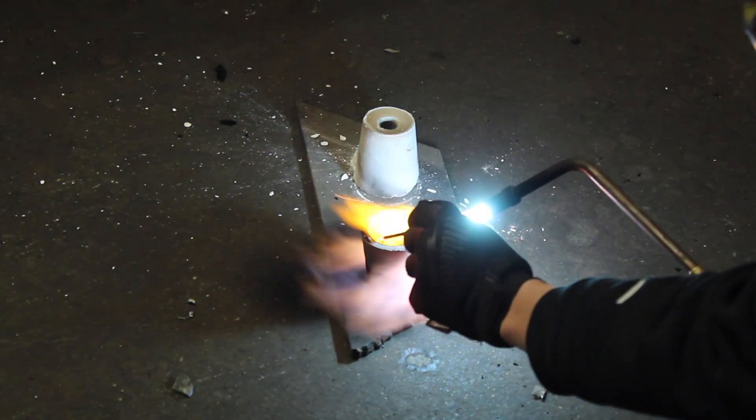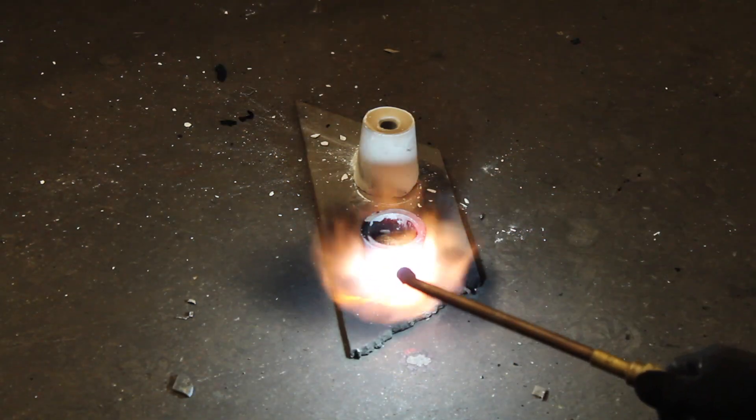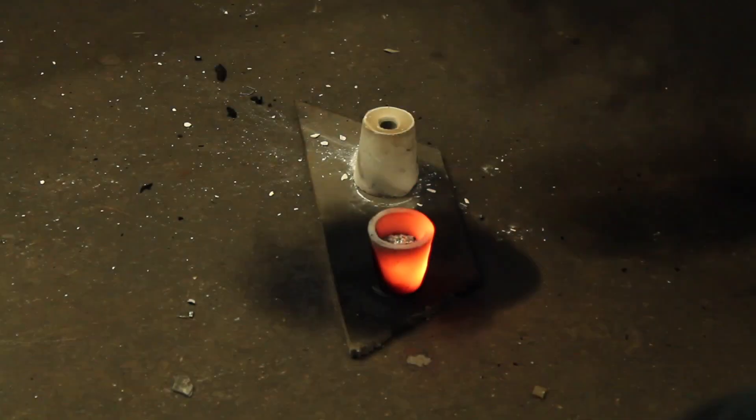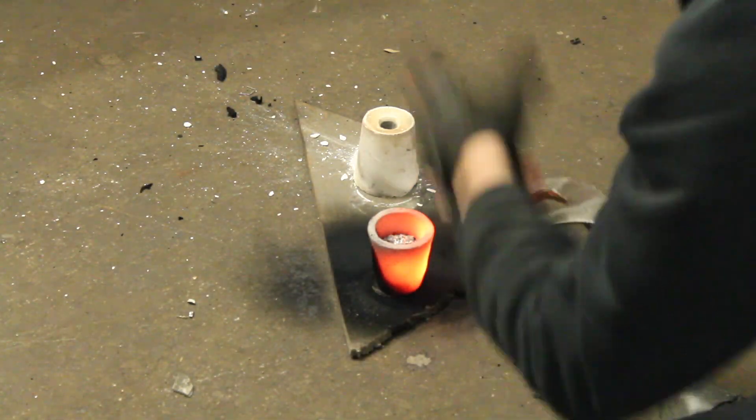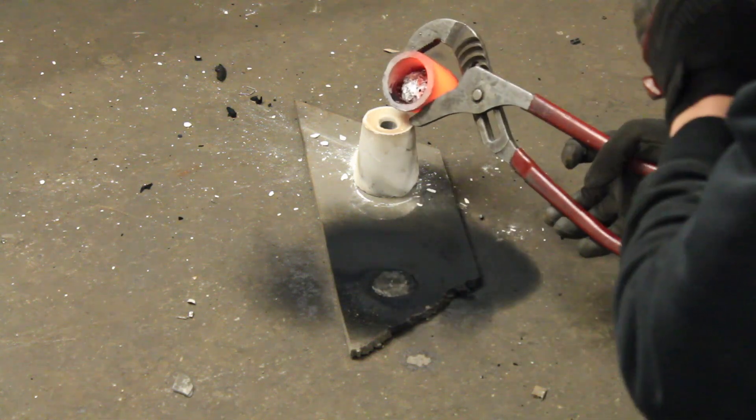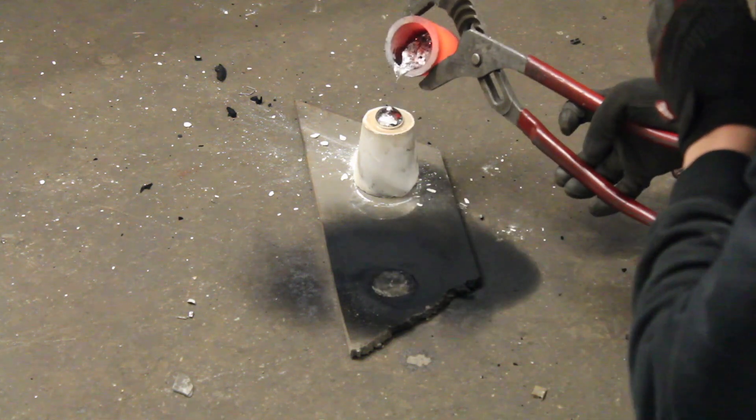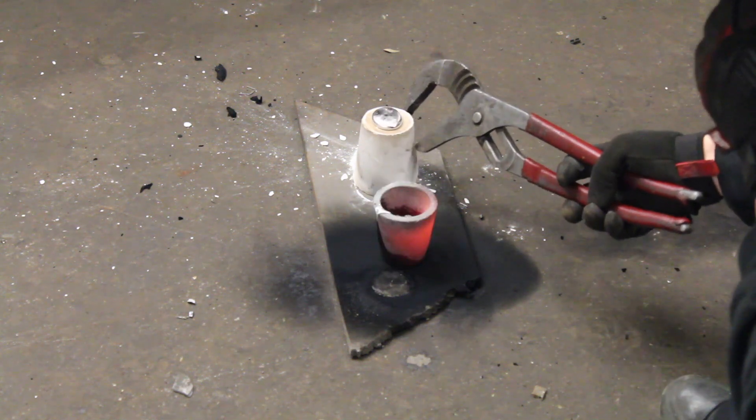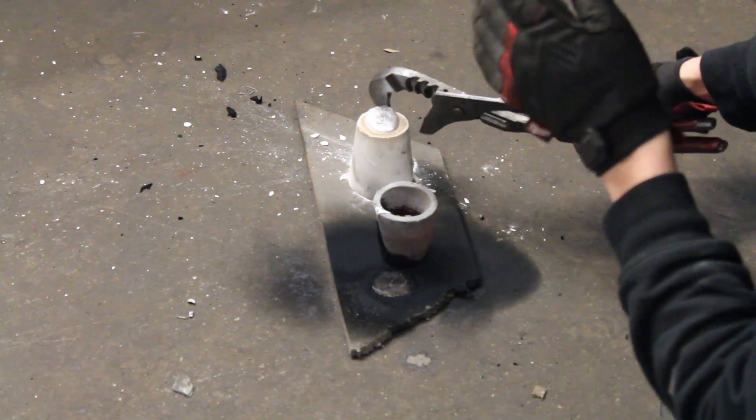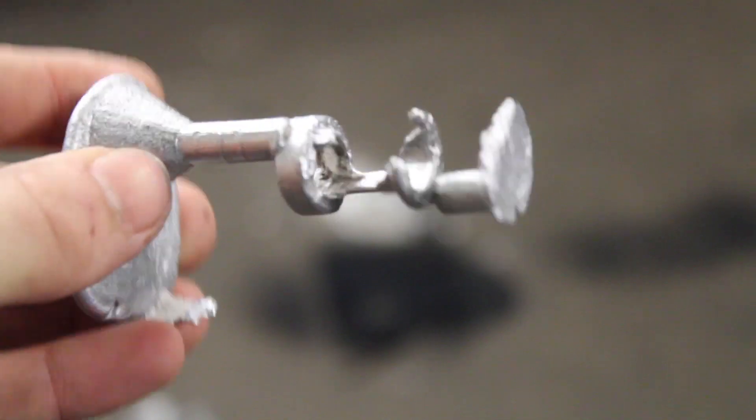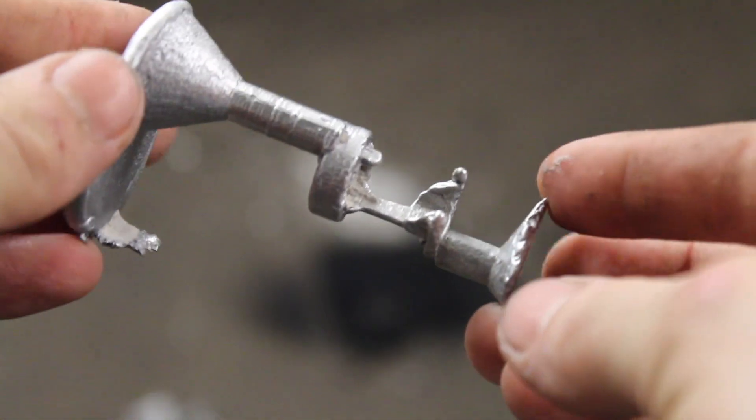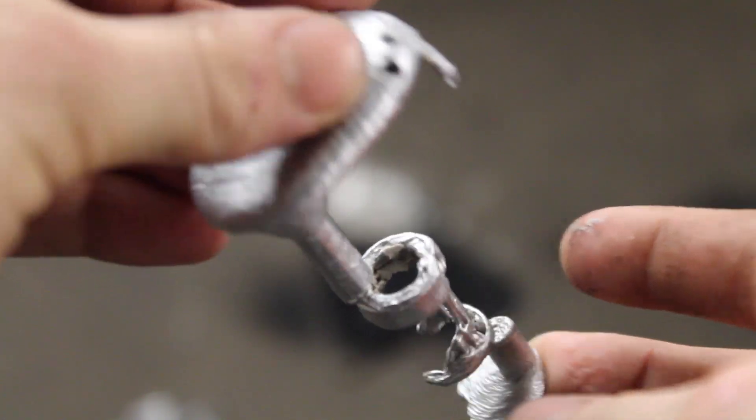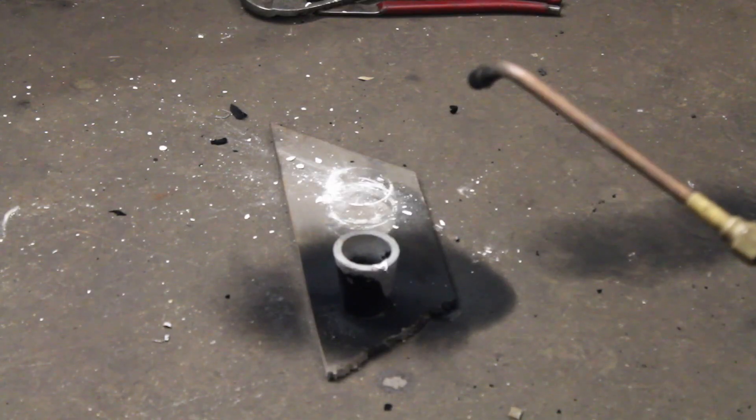And it ended up being pretty good. I got some good, it ended up working pretty well. I'm glad I used acetylene torch. It was much faster. It's probably like two or three minutes. Let's just use it still. So I basically, I did this a few times. I think I just didn't get the mold hot enough in these parts because these ones didn't work. I tried shaking it, tried shaking all of them. It actually just gives it a really shit surface finish when you shake it like that. Yeah, so it didn't go all the way down. I definitely think I'd blast the mold. That's one thing I did at the end that actually ended up seeming to help quite a bit. But this is a cool little trophy I could keep.